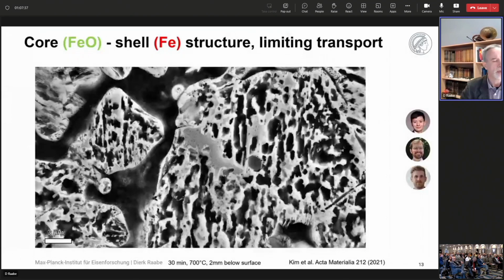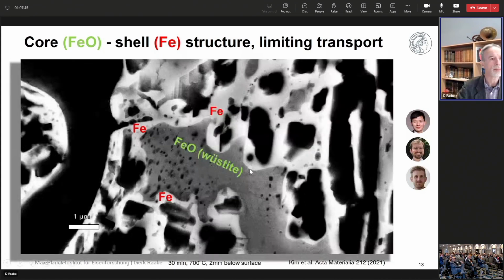So these are things that we just started to study really at a local scale in the electron microscope. When I now jump back to a polycrystalline material, that is a commercial hematite pellet, and I zoom in a little bit, now you cut that open, and you are at a late stage, after 30 minutes at 700 degrees centigrade under pure hydrogen exposure in a direct reduction setting. These are experiments by Jan Ma and Hauke.